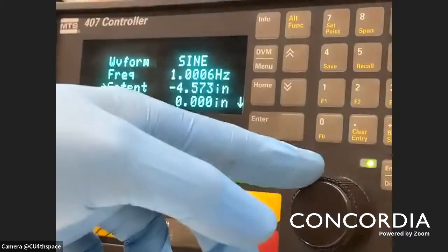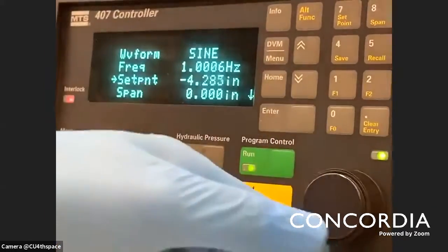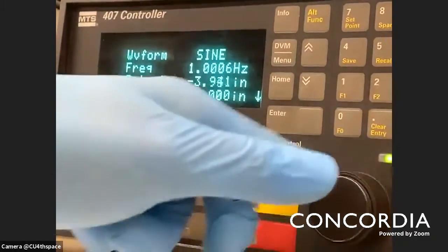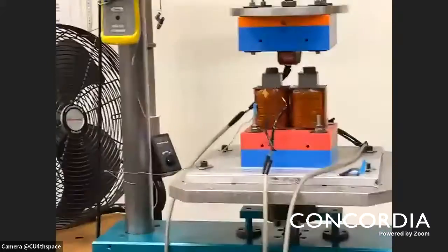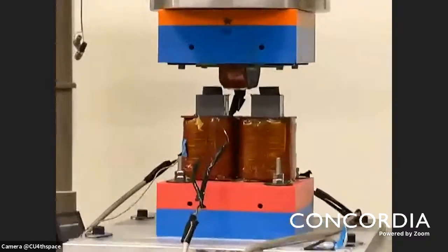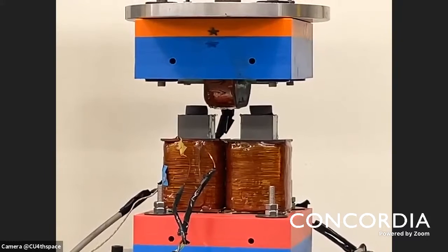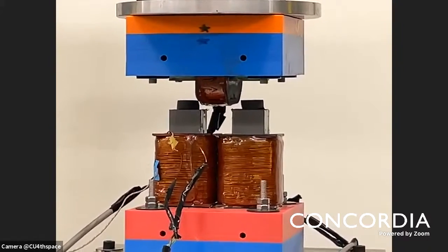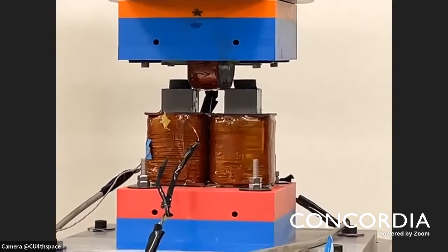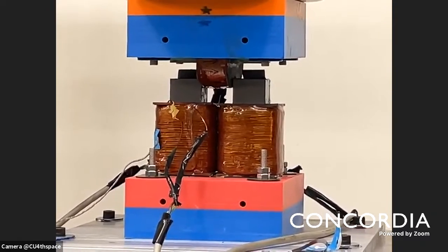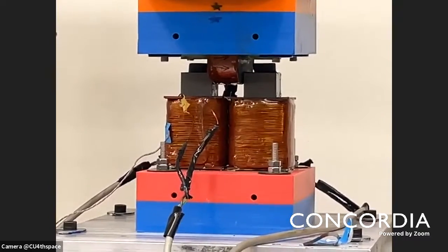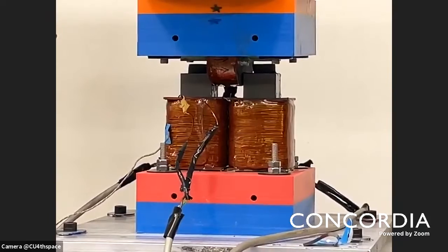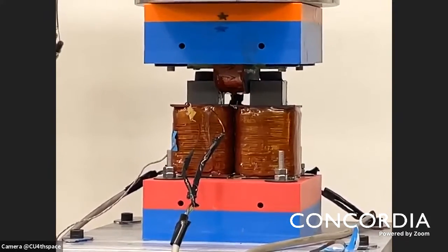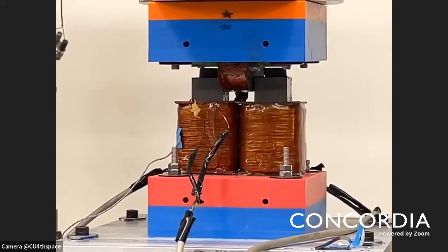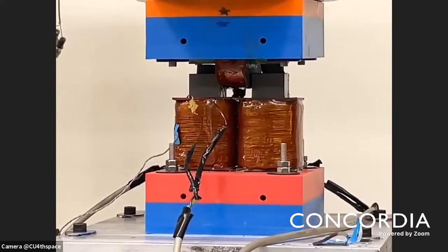For the start, I will put the sample. I displace the actuator upward, because from the top the sample will be connected to the yoke of the electromagnet. I will try to connect these two samples to the top, which is attached to the load cell from the top. Normally these materials experience a static deformation due to the payload, so there's a static pre-strain deformation. I will apply a 10% static pre-strain before applying harmonic oscillation.